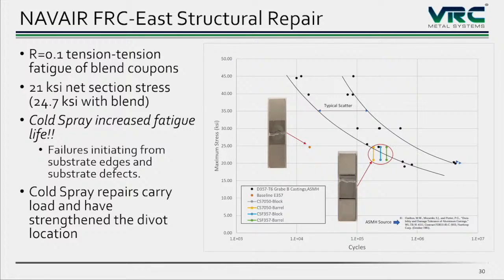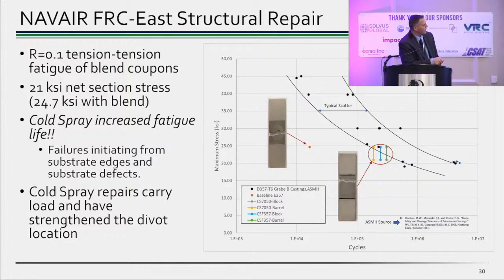So here you see an S-N curve for the coupons, and you can see what the coupons look like too. It's a kind of divot in the middle of the coupon. So our baseline again is the divoted coupon, and the goal is to achieve more cycles to failure, right? Increased cycles to failure. Here is the baseline sample, and then when we do our repair, we're actually pushing the cycles out to here. The scatter band there is actually for D357. It's not E357, but this is the only data we had available to us. So that's what I'm plotting. You can see we got an order of magnitude shift in the performance by doing this repair.